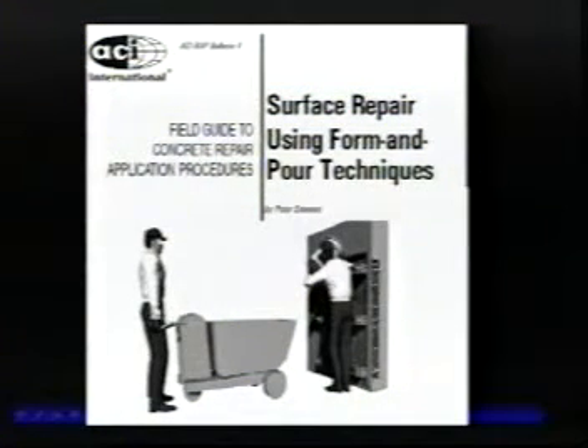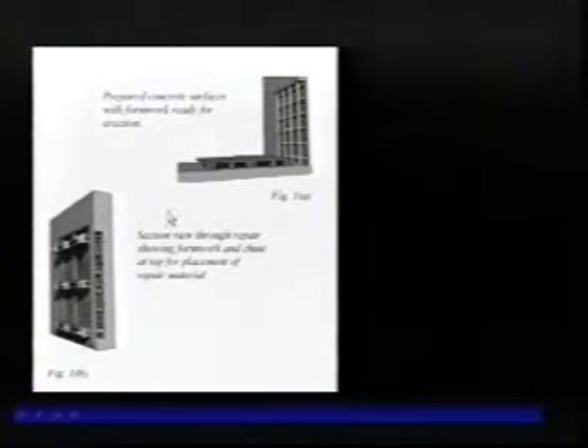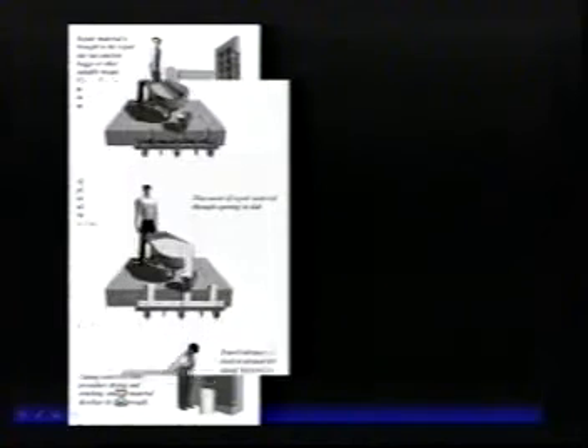If we look at the form and pour technique, which is basically building formwork, placing material behind it, and then consolidating it, these are some of the graphics that are in the RAP document. It's basically constructing formwork and placing the formwork up using some type of anchoring system. Again, this can be vertical or overhead. In this particular one, we're working on a wall. We're placing the material behind it, then we're going to vibrate it, and then we're going to strip it and make sure there's proper curing.